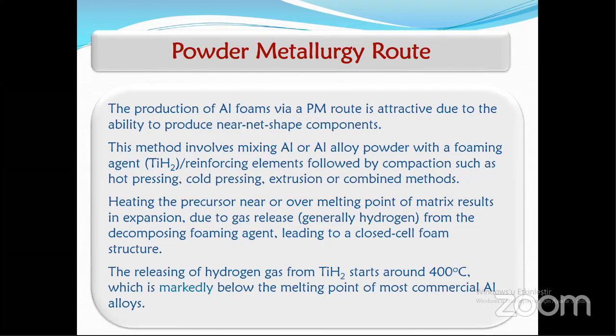When we look at the powder metallurgy route, the production of aluminum foams via this route is attractive due to the ability to produce near net shape components. This method involves mixing aluminum or aluminum alloy powder with a foaming agent. Generally, we are using titanium hydride, and reinforcing elements such as silicon carbide, boron carbide, aluminum oxide, etc., followed by compaction such as hot pressing, cold pressing, extrusion, or combined methods. Heating the precursor near or over the melting point of the matrix results in expansion due to the gas release from the decomposition of the foaming agent, leading to a closed cell foam structure.